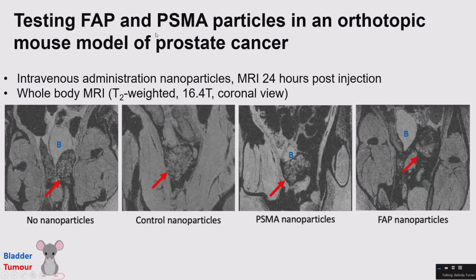So we tested the FAP and PSMA nanoparticles in an orthotopic mouse model of prostate cancer. What this means is we take an immunodeficient mouse and we inject human prostate cancer cells directly into the mouse prostate. You need a microscope for that one. It's quite fiddly. So it's kind of a humanized tumour growing in a mouse. After the tumour's grown for about 6 to 8 weeks, we intravenously administered the nanoparticles, and then 24 hours later, we performed MRI. What we're looking at here is a section of a whole body MRI of a mouse. We're looking around the lower abdomen and the legs here on either side.